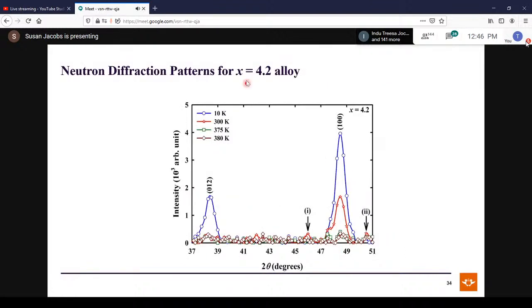Now, when we add vanadium, so the 4.2% alloy, once again, we see the magnetic peak, the 100 magnetic peak, which is suppressed as temperature is increased. Now, in addition to the magnetic peak, we see 2 satellite peaks, which are symmetrically displaced about the main magnetic peak. Now, vanadium is a very poor scatterer of neutrons, unfortunately. So these peaks are barely distinguishable above the background, but they are there and they appear at the calculated positions. So therefore, we believe that this system has satellites and it's the incommensurate phase.